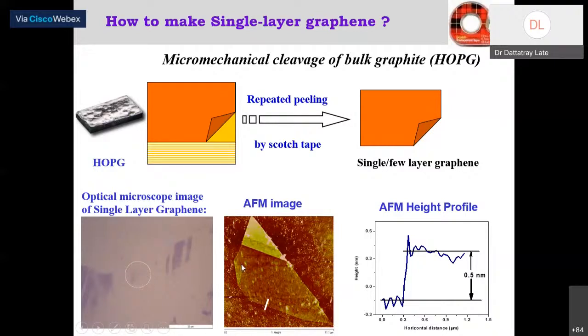These are multi-layer samples. Of course I can do atomic force microscopy to confirm the thickness of each individual layer, and find that this monolayer of graphene has a thickness of not less than 0.5 nanometer, because one layer of graphene is 0.34 nanometer. So this confirms that this is one layer of graphene. And then I can do other measurements to find out the thickness, and depending upon thickness I can tell how many layers are present in that graphene flake.